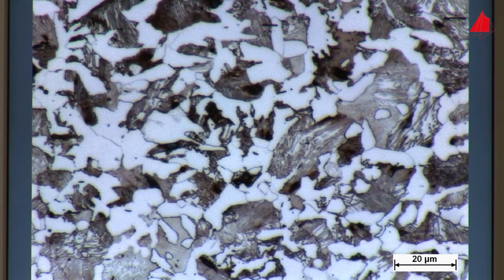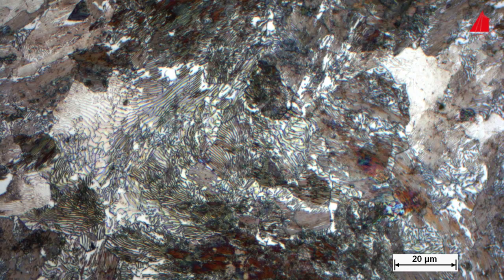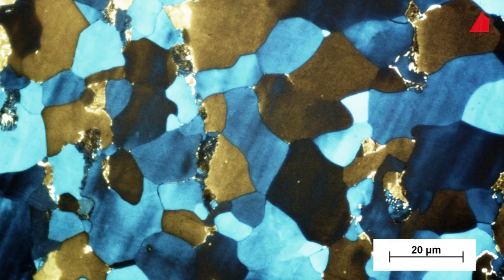In a similar manner, virtually all materials of our world may be examined. This is the plain carbon steel C80 with 0.8% of carbon. Only pearlitic regions with their characteristic alternating layers of ferrite and cementite can be seen. And this is the plain carbon steel S235 after a color etching. It only has a low carbon content. The relative amount of differently colored ferrite crystals is high, the proportion of pearlite regions low.